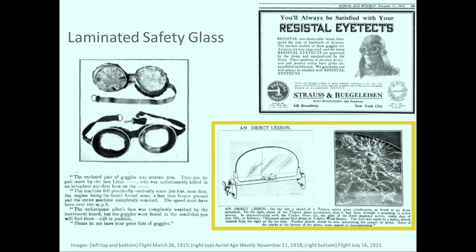Benedictus followed up with a series of improvement patents demonstrating the practical experience of the early production years, which effectively served as a period of research and development. The second patent, filed only eight months after the initial, describes the use of vacuum pressure rather than hydraulic pressure to compress the sandwich, allowing for cementing curved, arched, or convex glass. Triplex was expensive — non-standard thicknesses of glass had to be defect-free, and the work was done in very clean conditions. In 1924, one square foot would have cost about 10 to 12 dollars. World War I provided a major incentive for developing Triplex into airplane and automobile windshields, bulletproof glass for tanks, glass for submarines, battleship bridge windows, and eye blanks for gas masks and aviator goggles.